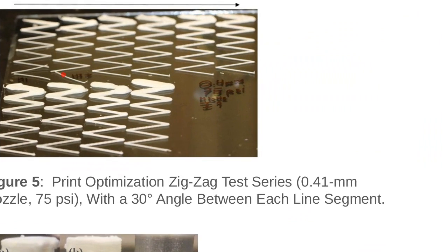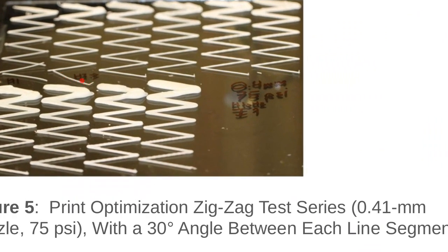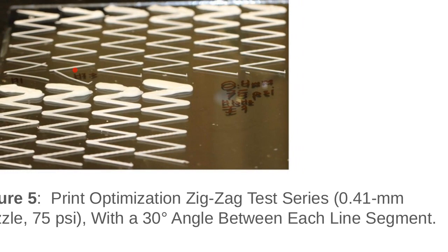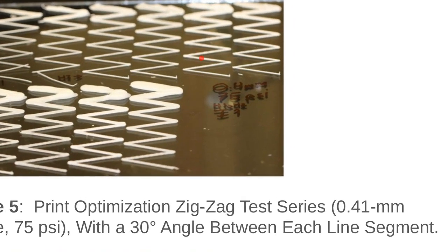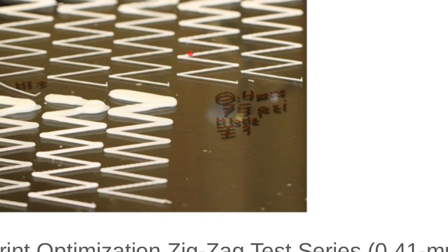Jorge's currently highlighting one, to note one of those qualitative aspects that we're talking about, where it was a very nice and fine bead and close to that nozzle diameter on paper. But realistically, that qualitative assessment would tell us that it's not very good because it barely stuck to the actual substrate and came off easily. Right, and Jorge is now currently pointing to another aspect that we noted in our qualitative assessment of these beads, where we had these strange printing artifacts in which it appeared like pulsing, that we made a note of.